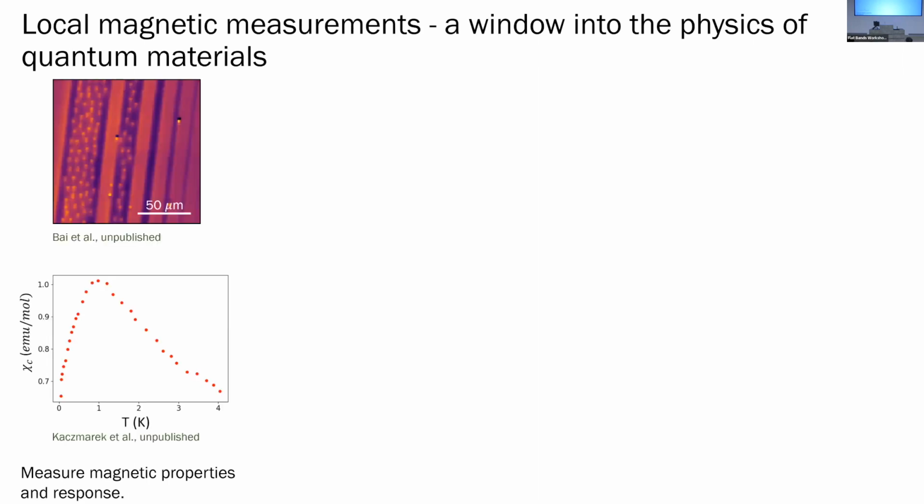So if you think about a magnetic probe, you probably think, well, I can measure magnetic properties and maybe also the magnetic response. And so, for example, using DC magnetometry, you can look at vortices hanging out in superconducting, in this case, niobium titanium nitride strips. This is interesting to our collaborators at IMEC who work on superconducting digital circuits made from niobium titanium nitride.